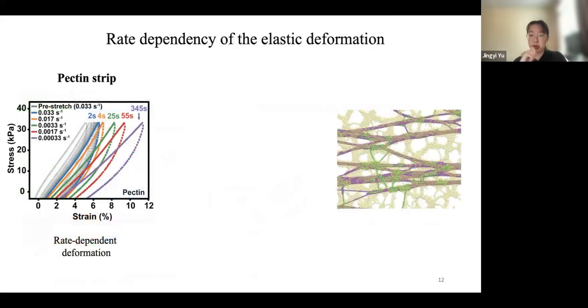The first thing you can imagine, similar to the analogy I just mentioned, is that the cellulose microfibrils we can almost treat like parallel and intertwined elastic springs, stretched inside the pectin, which is the major viscous component in the plant cell wall. So the first test we did is to stretch pure pectin strips to see if the pectin is indeed a viscous or viscoelastic material.